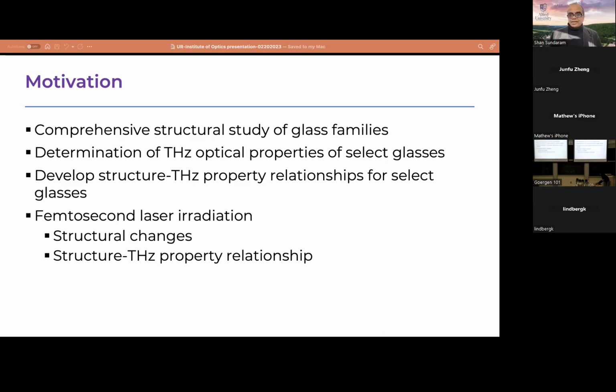The idea behind that is I will use laser pulses, I will deposit a certain level of energy locally, part of which will thermalize and it will change the glass structure in the location. Then I'll be able to track the changes in properties. If I can do that, then not only can I make a specific glass composition, a piece of glass with specific terahertz properties, I may be able to also locally modify it by using femtosecond pulse laser or any other means of processing tool.